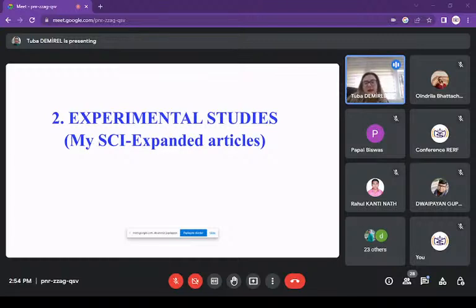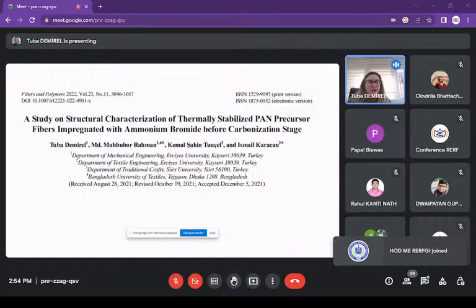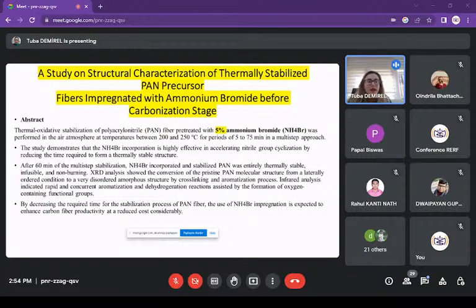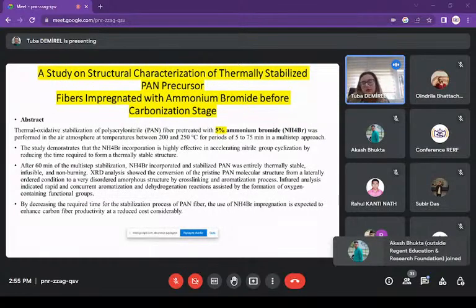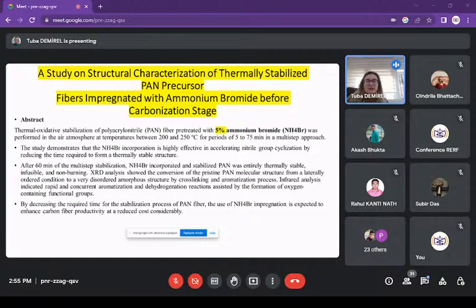Experimental studies: my SCI-expanded articles, I explain first my article, a study on the structural characterization of thermally stabilized PAN precursor fibers impregnated with ammonium bromide before the carbonization stage. The thermal oxidative stabilization of polyacrylonitrile PAN fiber pre-treated with ammonium bromide 5% was performed in an air atmosphere at temperatures between 200 and 250 centigrade for periods of 5 to 75 minutes in a multi-step approach.